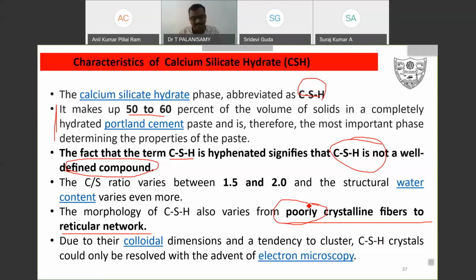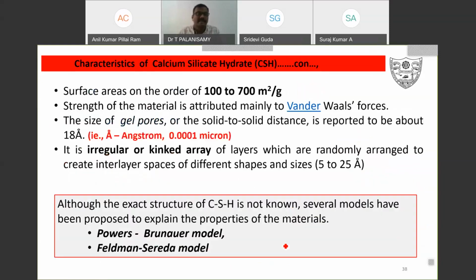Due to their colloidal dimensions and the tendency to cluster, CSH crystals could only be resolved with electron microscopy. The surface area is on the order of 100 to 700 square meters per gram. The strength of the material is attributed mainly to van der Waals forces. Suppose any chemistry researchers want to do research: if I add some mineral admixtures into that cement paste, how will it change the van der Waals forces? You can find the size of the gel pores, with a solid-to-solid distance reported at about 18 Angstrom, which is nothing but 0.0001 micron.